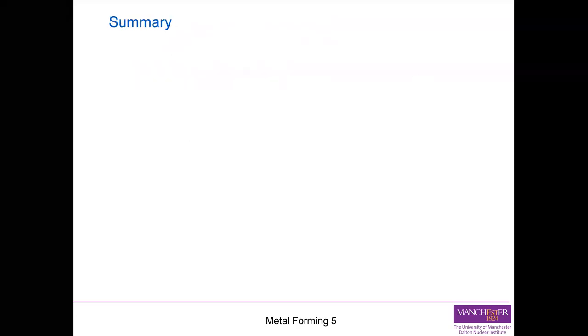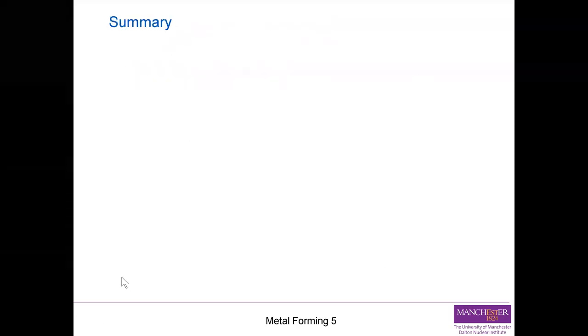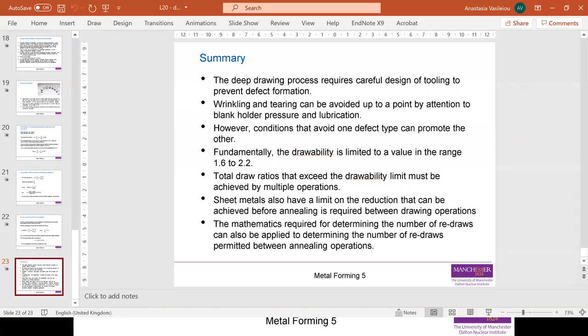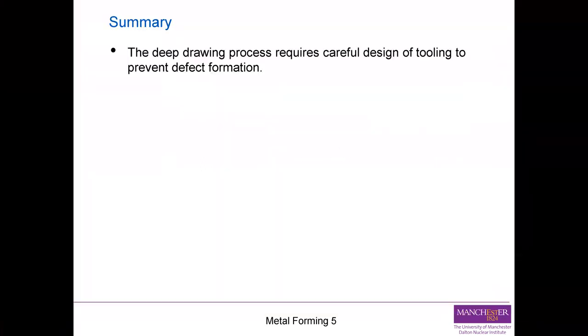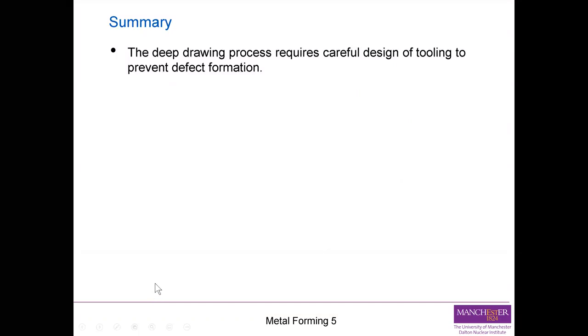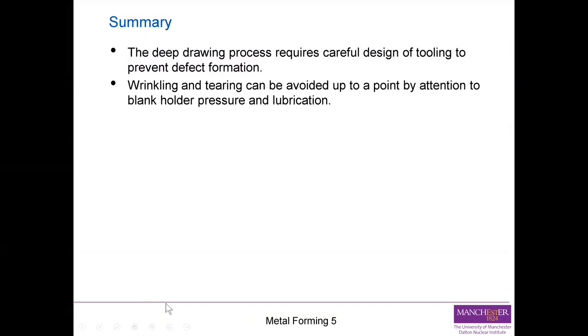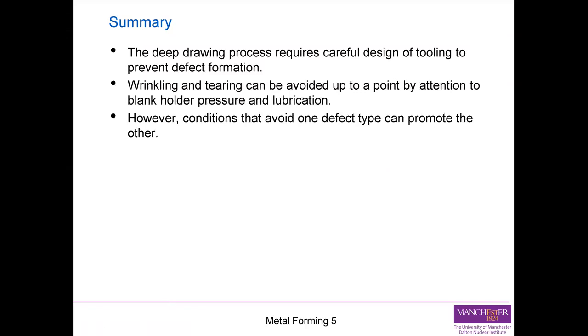So to wrap up this lecture, I will summarize in this final slide. The deep drawing process requires careful design of tooling to prevent defect formation. Wrinkling and tearing can be avoided up to a point by attention to blank holder pressure and lubrication. However, conditions that avoid one type can promote the other.